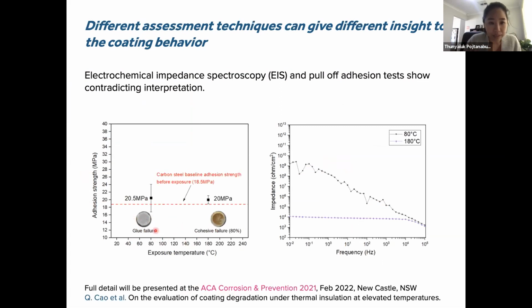For example, here on the x-axis we have exposure temperature, and on the y-axis we have the adhesion strength. When the coating was exposed at the lower end of the temperature, 60 to 80 degrees, the adhesion strength was quite high, even after 6 cycles of the Houston pipe test, so wet and dry cycles. The adhesion strength is still over 20 MPa, and that is similar to the baseline, which is highlighted in the dash line here. So it didn't change with time.